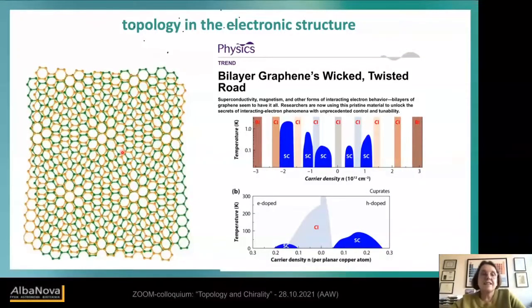And then, if we have these two layers which are twisted, they show very distinguished properties from graphene itself. It shows superconductivity and an insulating state. And from my viewpoint, I think this can also be interpreted by simply thinking about aromaticity, where you have areas which are aromatic and areas which are anti-aromatic, which are localized, and which are also reflected in these superconducting areas and insulating areas.